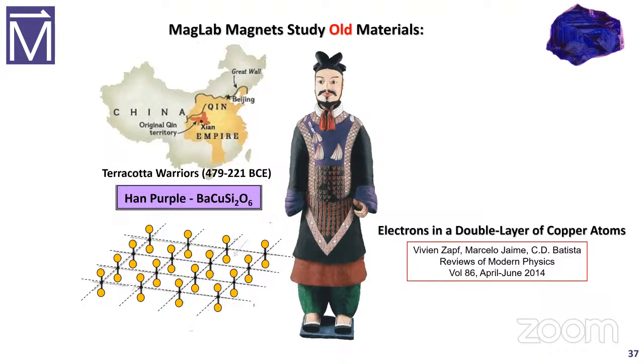And they started doing a literature search once they started getting interesting information, and they turned up all kinds of papers from archaeology journals that were talking about this Han purple. So they had accidentally, because they were interested in analogs to high temperature superconducting systems, stumbled across something that the Chinese had known about for hundreds and thousands of years. Because it turns out that this system in Han purple is a quasi-two-dimensional magnetic insulator with a gapped spin dimer ground state. And we're pretty sure that they didn't know that.